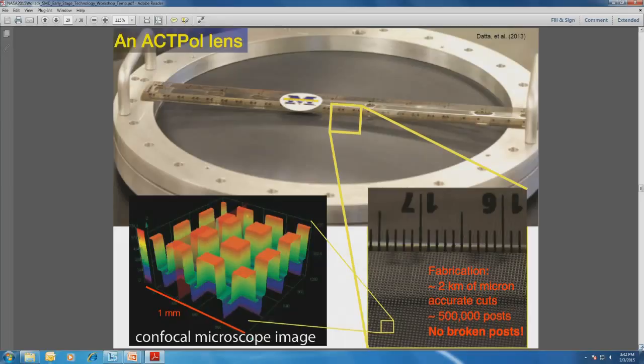It holds our tolerance, the uniformity of the material. You have to cut it uniformly on X and Y, otherwise it'll become birefringent. You could use that to your advantage if you wanted to make something, but in our case, for this particular application, we do not want it to have birefringence or biattenuance.